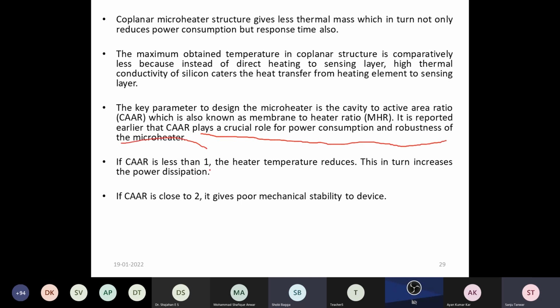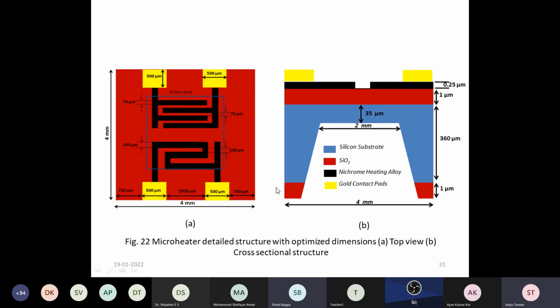If it is less than 1, the heater temperature reduces, which in turn increases the power consumption, while if it is close to 2, it gives you poor mechanical stability. Therefore, we keep it between 1 and 2 because we want higher mechanical stability as well as lower power dissipation.